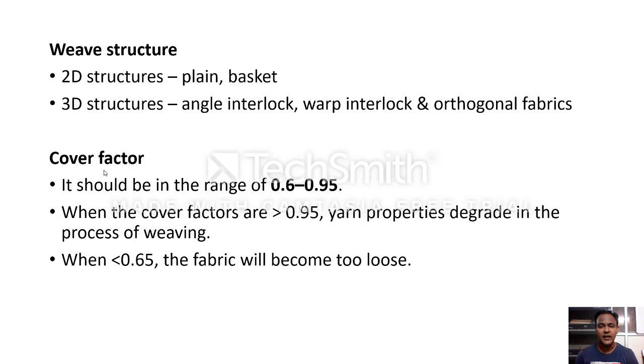Number of warp and weft, when it is completely more, if it is occupying, then we can say the cover factor is high. So cover factor should be in the range of 0.6 to 0.95. This is based on some experimental results, these values were given. So the cover factor should not be too low or too high.